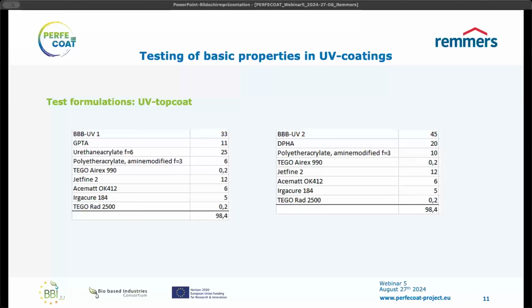And on the other side, bio-based binder number 2, the 45% which we have here in the recipe, that means 55% on organic part. So in these recipes, you can see that it's possible to add quite a significant amount of this newly synthesized PERFECOAT binders into a UV curable formulation.